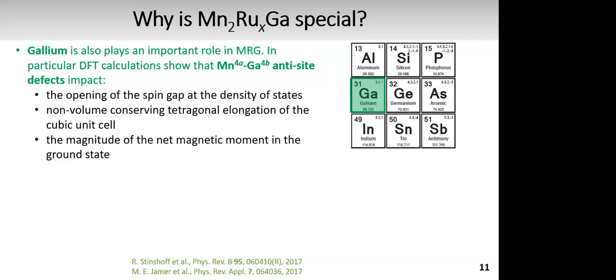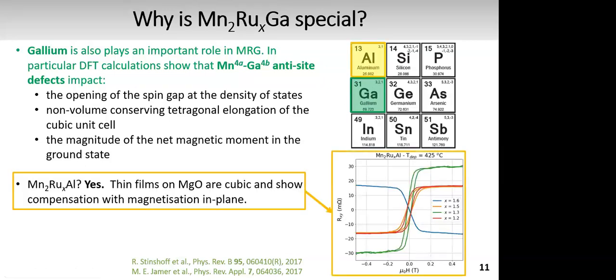And of course, again, considering our Slater-Pauling rule, it would be a natural choice to try to replace gallium with aluminium. And this is indeed a zero moment half metal. This is my own work that I have done showing here anomalous Hall effect loops for various ruthenium contents. And we see this characteristic change of sign of the anomalous Hall effect coefficient as we cross compensation.